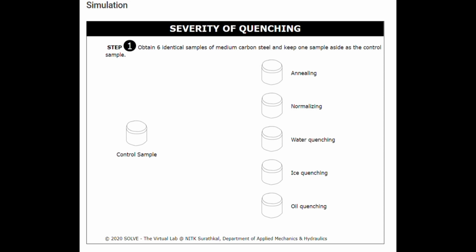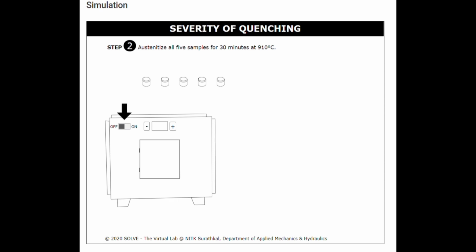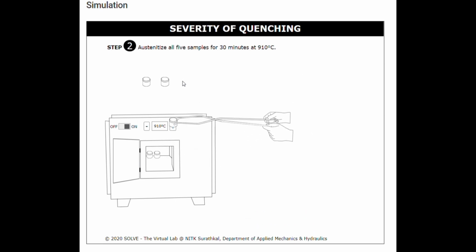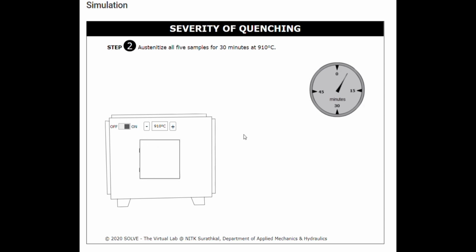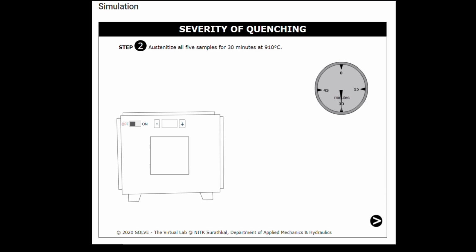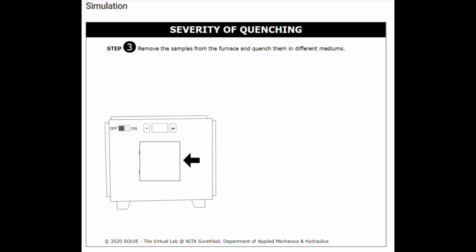In step 1, we obtain 6 identical samples of medium carbon steel and keep one sample aside as the control sample. In step 2, we austenize all 5 samples for 30 minutes at 910 degrees Celsius. Then we wait for 30 minutes. The next step is we remove all the samples from the furnace and quench them in different mediums.